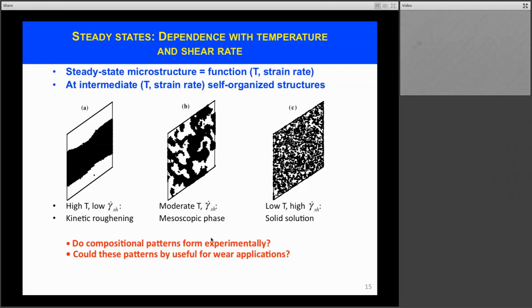And so the next two questions that I would like to address are, one, do these compositional patterns form experimentally? And could we use these patterning reactions in a useful manner for wear applications? The main point is that I put check marks on the left and right steady states, because as I showed you before, from X-ray diffraction, we know that these were the steady states observed during ball milling of copper silver at very low temperature and at elevated temperature.